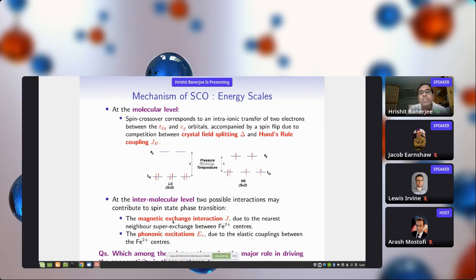Well, mostly it has been identified that the two possible interactions could be the magnetic exchange interaction J between the nearest neighbor, superexchange between Fe2+ centers, and the phononic excitations E el due to the elastic couplings between the Fe2+ centers. So which among them plays a major role in driving the cooperativity in the system? That is what we want to figure out.